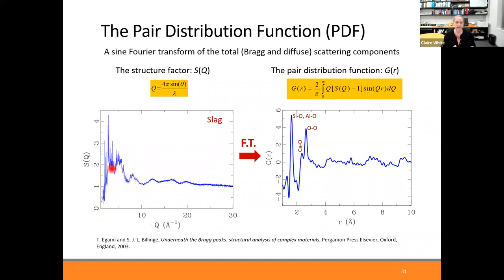And so here we're going out to high Q. If you think about a lab X-ray diffractometer using copper as the wavelength, so a copper X-ray tube, the highest Q max you can get is out to 8. So at synchrotron and neutron facilities, you can get to much higher Q max values. You can cover more of momentum transfer, which means when you Fourier transform the data, you end up with better resolution in real space.